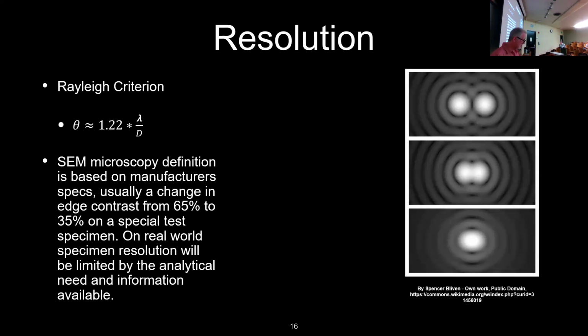The SEM and FIB microscopy definitions, like I say, I think we lie a little bit here because we use edge contrast methodology, which means there's a test specimen like I showed you previously, although we would use gold carbon for this microscope because it's extreme high resolution. And we look for a change in contrast from 65% to 35%. Rayleigh criterion would imply that we have to go from 90% to 10%. And so our 0.5 nanometer resolution might mean we can see particles maybe 3 or 4 nanometers in size.